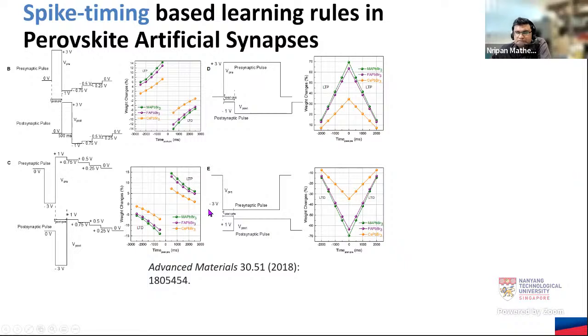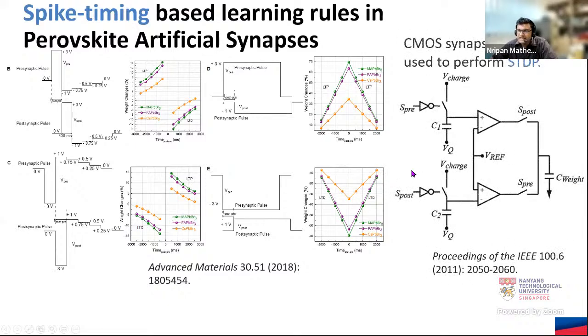We were successful in doing so, and we were able to emulate the different learning rules, including spike time dependent plasticity, where depending on whether the postsynaptic pulse or the presynaptic pulse arrives first, you are able to modulate the weight changes. We were able to study this for all the different materials, and we saw that the synaptic activity seems to be stronger for the organic based one rather than the inorganic based one. Again, just to recap, normally a CMOS would require a couple of capacitors and op-amps to do such an emulation, while here we are doing it with a single device. But again, to be fair, every memristor would be able to do something similar.